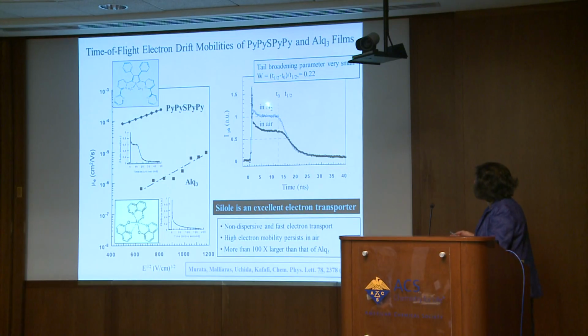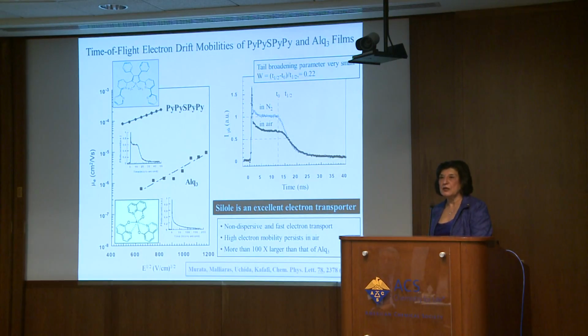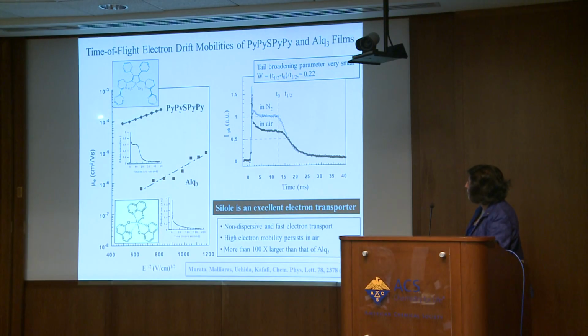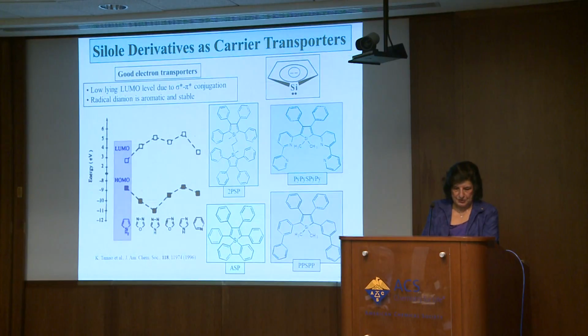And here I show you a textbook example of an electron transporter, which is this silicon-based compound. You see here the time of flight, where you see the peak, and then in either nitrogen or air, you get this plateau, and then it goes down. This is really a textbook example of a non-dispersive carrier of charge. So its transport is non-dispersive and it's very fast. We were able to determine its mobility, which was much, much higher than that of Alq3 at the time, which was the reference that everybody used.